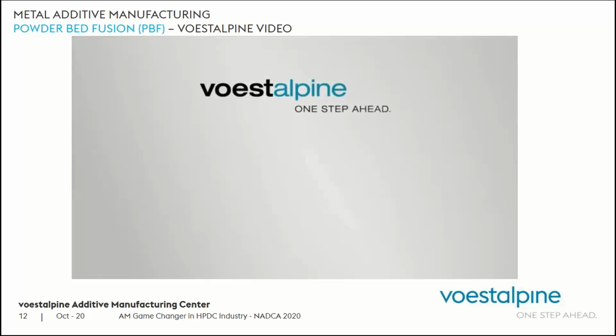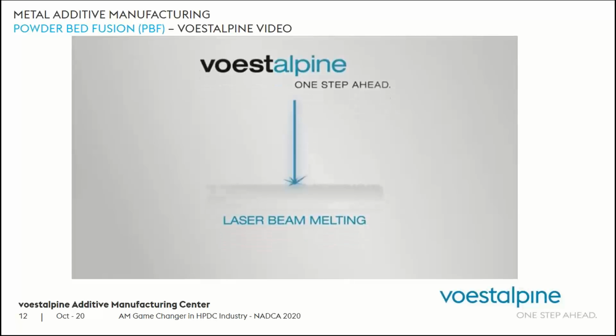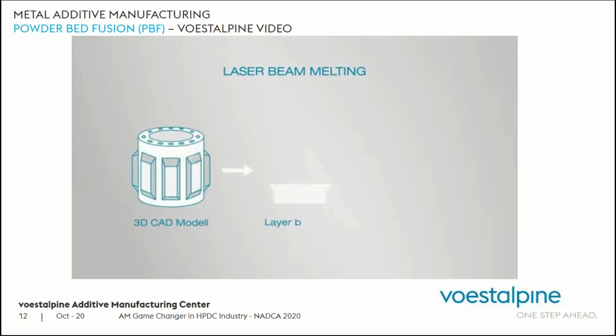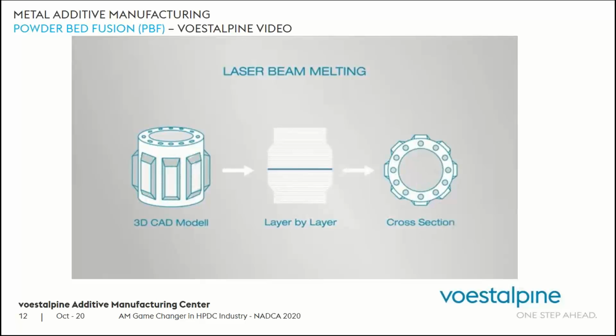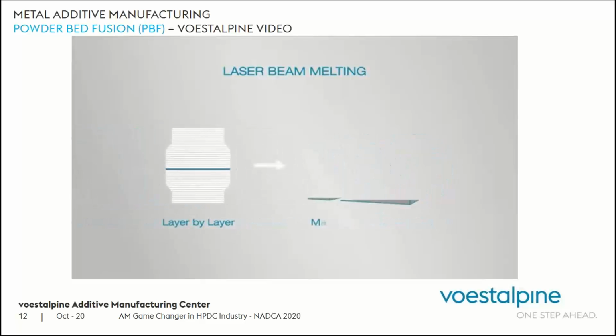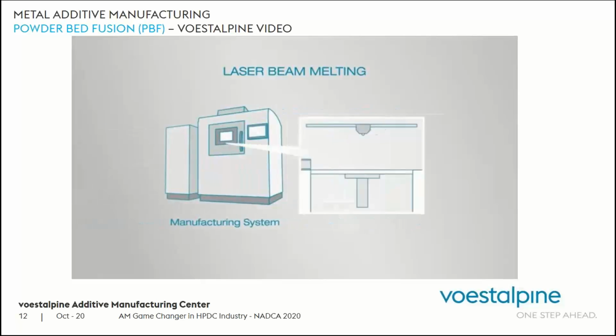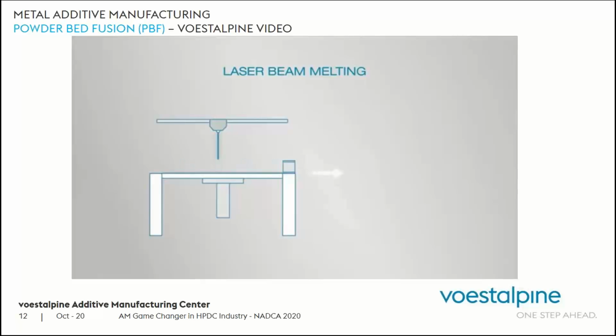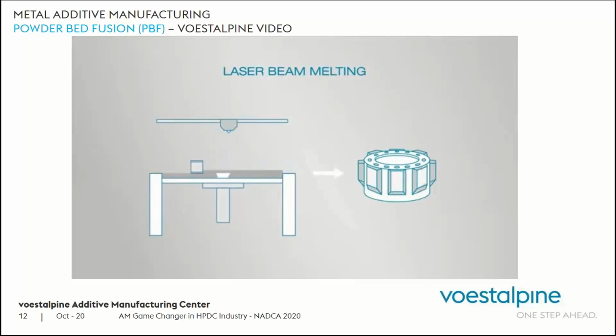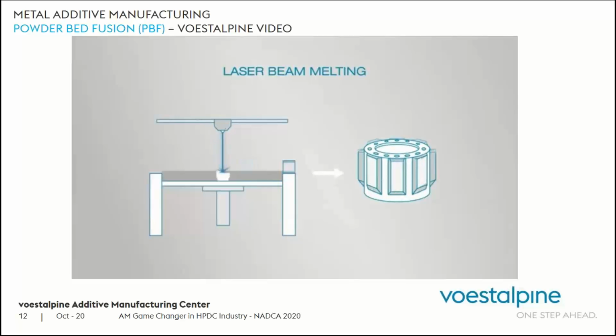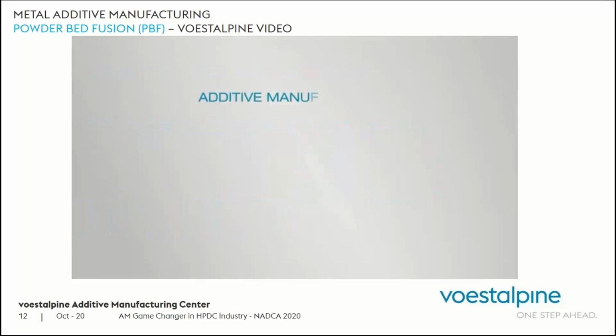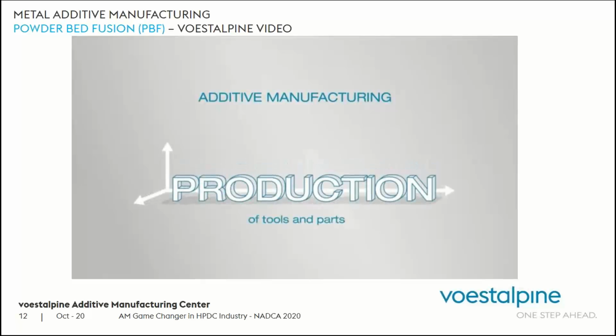At voestalpine, we use the so-called laser beam melting process. The first step is to slice a 3D CAD model of the designed component into cross-sections. This data is transferred to the additive manufacturing system, where a laser melts each section in 20 to 100 micron layers of metal powder from the bottom up until the part or prototype with full density is built. Additive manufacturing opens the door to a world of new possibilities in the production of tools and parts.